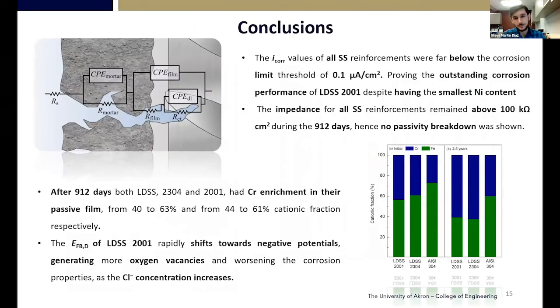So as a summary, over these 2.5 years of exposure of the concrete samples for our 3 different stainless steels, we saw that all 3 stainless steels were able to stand way below the 0.1 microampere per centimeter square, proving their outstanding corrosion protection. We also saw that the duplex stainless steel was able to withstand the chloride amount and show that there was no passivity breakdown over these 2.5 years, because of the 100 kilo ohm centimeter square throughout the entire testing.